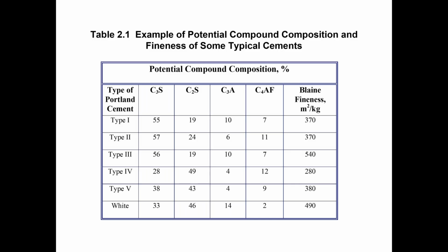Looking at the type 5 cement there, type 5 cement has a higher sulfate resistance. So one of the key differences in the type 5 is that low C3A. So keeping the C3A low, because that contributes to sulfate attack. So that's the key thing there, is the low C3A.